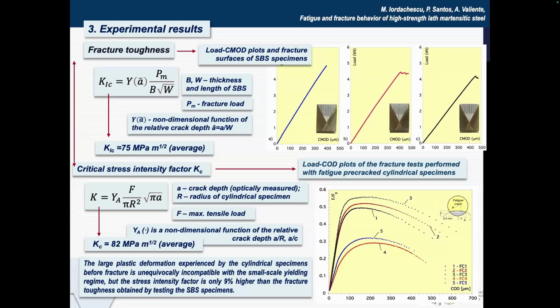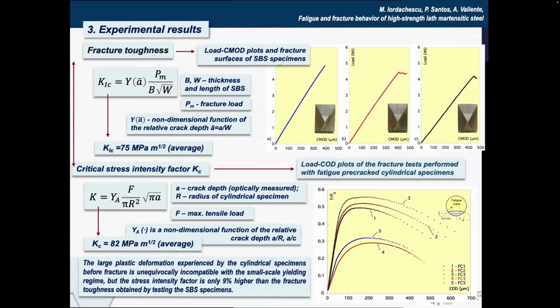Now, what you have to understand is that here we are seeing large plastic deformation experienced by the specimens, and clearly this is incompatible with small-scale yielding. But the stress intensity factor computed with this equation is only 9% higher than the fracture toughness that we obtained with, let's say, standard specimens. Going further,